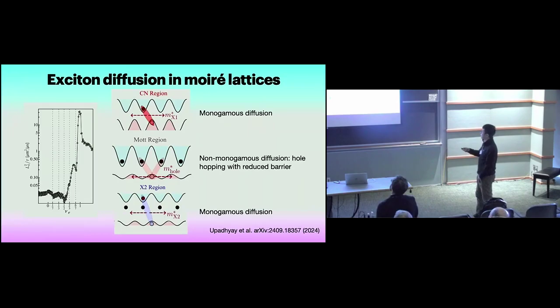And once you overdope the system above mu equals 1, you recover the initial state, but now you have a multi-exciton diffusion, where two electrons are on the same lattice site. So this actually provides a quite intuitive picture of why we see this dramatic enhancement of diffusion at this particular region. Yes?